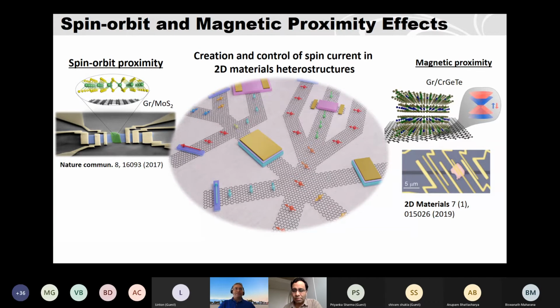And about other things, there have been some studies with graphene where they put some gold and other materials by evaporation and study what is happening in the RPS. With van der Waals heterostructures it's quite limited by the flake sizes, and one actually needs micro RPS, called nano RPS. That will be helpful. But graphene with a 2D magnet will be a bit difficult to investigate because you may need graphene on top to protect the magnet, since they are quite reactive. But graphene with TMDs, MoS2, tungsten sulfide are quite stable for a few days, so that can be done.